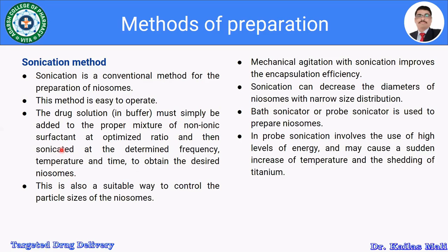So simply here, we have to prepare the drug solution in buffer and add it to the proper mixture of a non-ionic surfactant at optimized ratio, and then sonicate at a determined frequency, temperature, and time to obtain the desired Niosome. This is also a suitable way to control the particle size of the Niosome by changing the frequency, temperature, and the time. Mechanical agitation with sonication improves the encapsulation efficiency. Simultaneously, if we are agitating the solution along with the sonication, it will improve the encapsulation efficiency of the product.